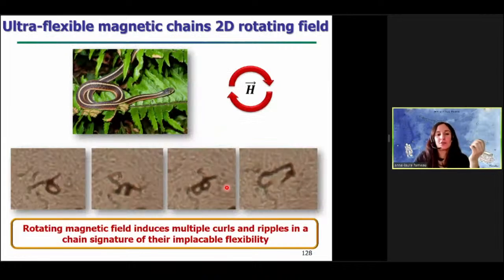And then to also study the flexibility of this magnetic chain, we put one single chain in a two-dimension magnetic field. So like this. And as you can see here in this picture, we can see the formation of one curl and even two curls, and the chain doesn't break. So that shows the ultra flexibility of this chain. And why? It's because all nanoparticles are surrounded by a fluid layer of fatty acids, so they enable a perfect rollover of the particles from each other. So you have very, very high flexibility of this kind of filaments.